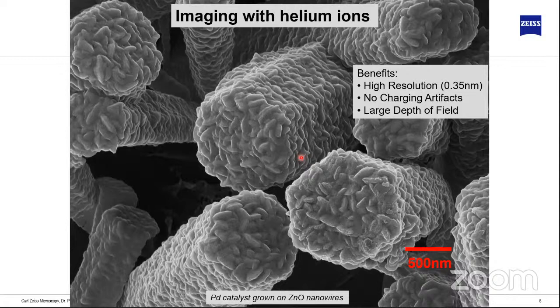If we take images with a helium ion microscope, what we typically see is a very strong surface detail, so you can see very fine structures here on the surface with excellent resolution. What we also see is we have an extremely good depth of field, so that means the sample is in focus on the top, all the way down to the bottom, we are in focus. So we can also see these structures here at the bottom, so it's very, very easy to image something because you focus on some area of your sample and you always stay in focus, which is really nice.